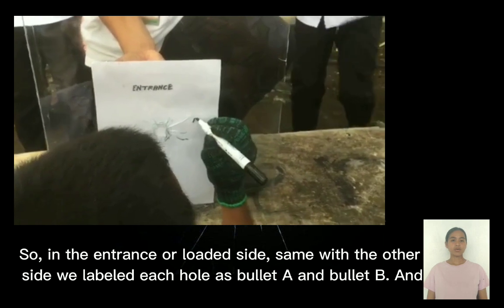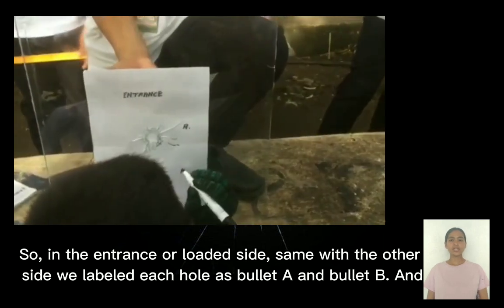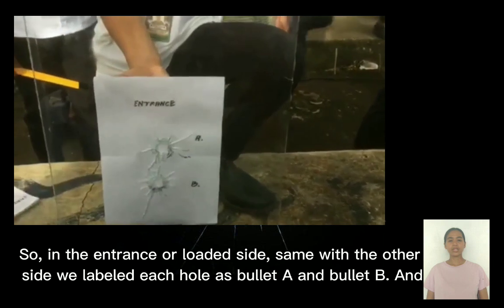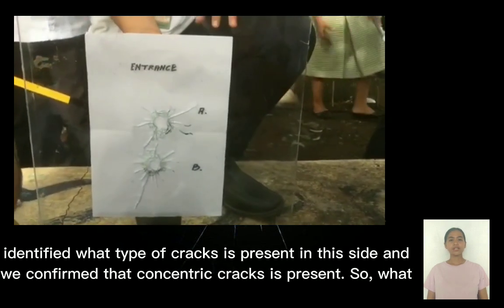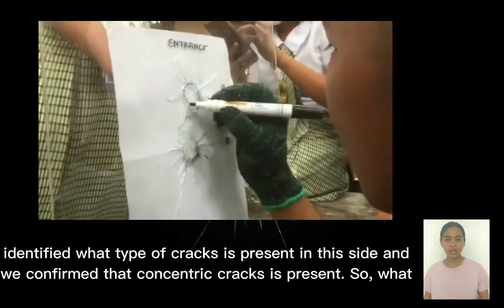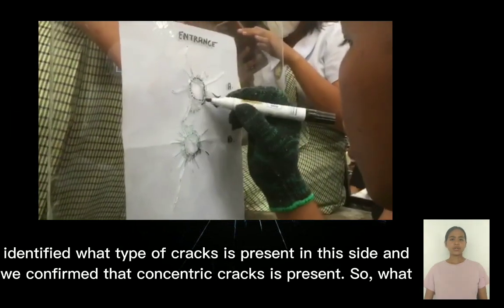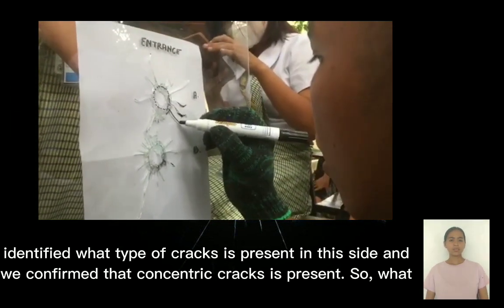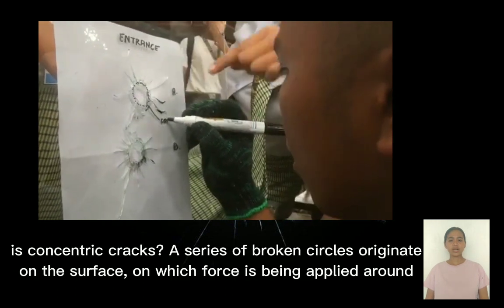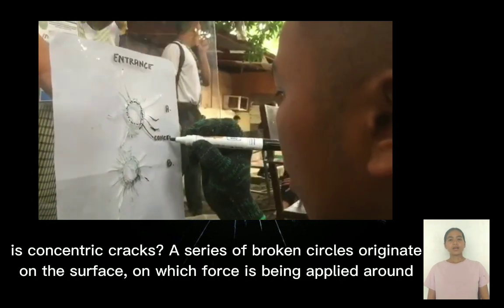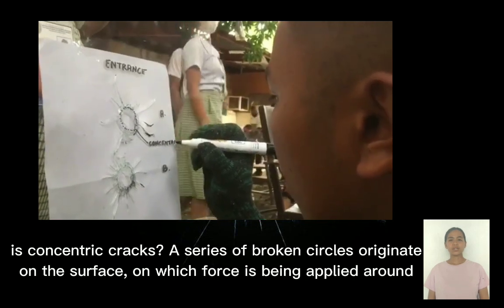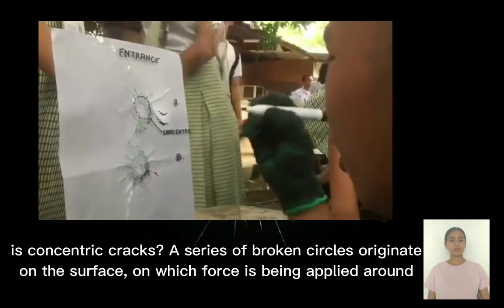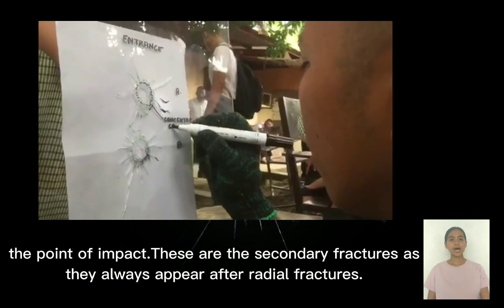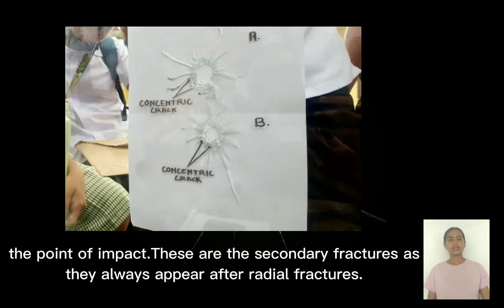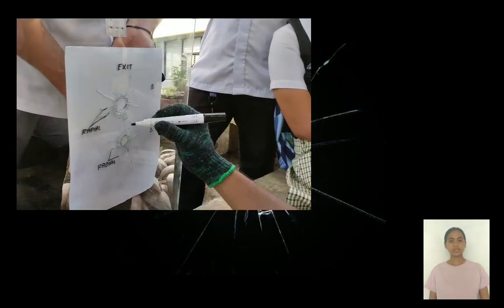So on the entrance or loaded side, same with the other side, we labeled each hole as bullet A and bullet B and identified what type of crack is present. On this side, we confirmed that concentric cracks are present. So what are concentric cracks? A series of broken circles originate on the surface on which force is being applied, around the point of impact. These are secondary fractures, as they always appear after radial fractures.